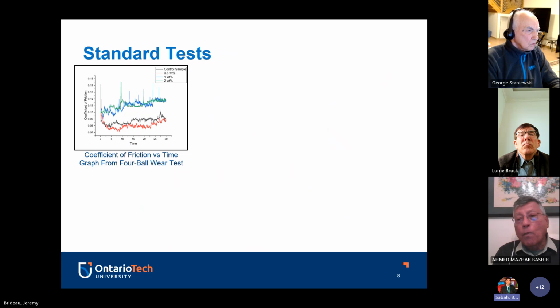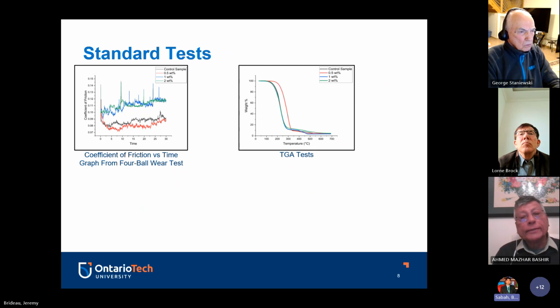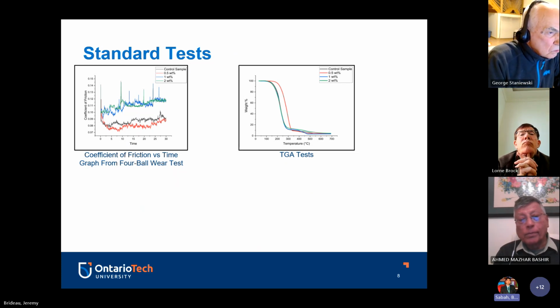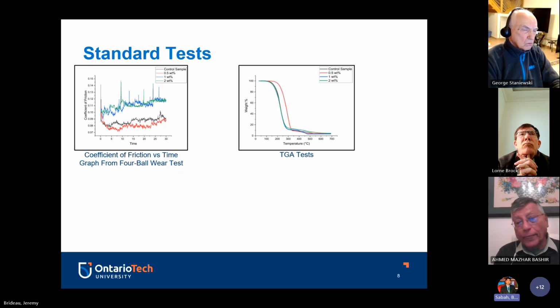As well as the next test that we had was the TGA test. Now, this test was extremely valuable for us. For those of you who don't know what a TGA test is, basically you put around 5 milligrams of grease onto a little pan, and then you heat it up to about 700 degrees Celsius. And you see how fast or how slow the grease itself degrades or disintegrates. So what we noticed was when we had the 0.5% weight percent, it actually degraded at 50 degrees warmer than all the other ones. This is due to graphene creating a lattice type structure that is a lot more challenging to break down than when just a standard grease is used.